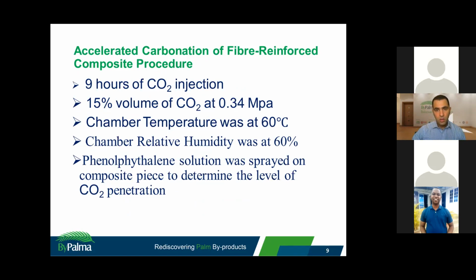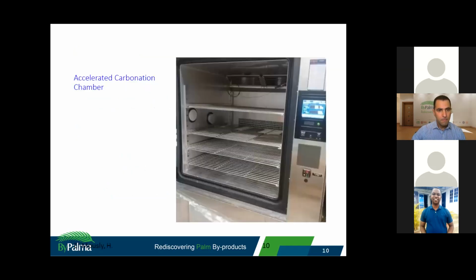Now, the chamber is at 60 degrees Celsius, and the relative humidity of the chamber is 60%. Then something was introduced to determine the level of penetration of CO2, to see how deep the CO2 is injected into the sample, how deep it is in the composite material. Now, this is our carbonation chamber. All the samples were loaded, you close the chamber, and it's automated. So we regulate it, and then after the 9 hours, you bring out your sample.